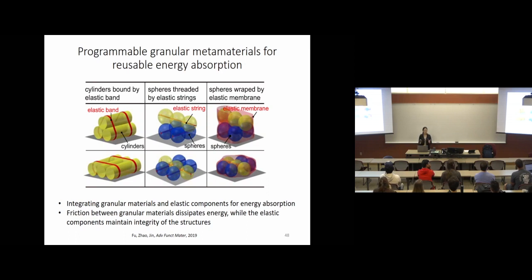Next, I'm going to briefly talk about a second idea. The main question is, what kind of mechanism can dissipate energy but not cause damage to the material? The second mechanism we are harnessing is friction. We are making this so-called programmable granular metamaterial. We have a few different designs, but the main idea is a granular material together with elastic components, elastic bands and strings, such that the relative motion of the granules can dissipate energy, while the elastic components maintain the integrity. Once you unload the material, it can recover its original shape.